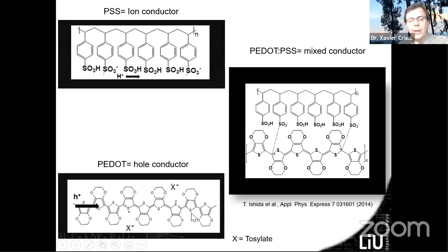The one on the bottom here is a derivative of polythiophene, and what you can look at is that there is an alternation of single and double bonds in the backbone of the polymer chain. This makes this polymer a conjugated polymer, which in that case is oxidized. That is to say, it carries also positive electronic charge on the chain, which is balanced by counterions that are here symbolized by the X minus, in order to have a neutral material.